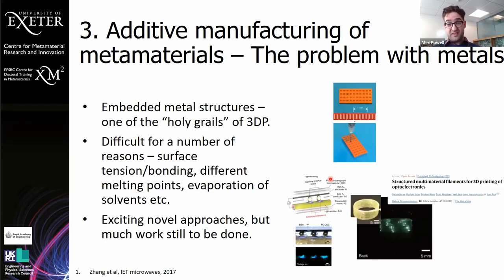In terms of embedding structures, this is still something that's really, really difficult. And I would say that there's a lot of people working on different methods for this, but as far as I'm aware, a satisfactory way to make metal inclusions still remains to be achieved. And it's really difficult for a number of reasons. Like, you have to have surface bonding between your different layers. So this is actually quite hard to achieve between a lot of different metals and different materials. They also have radically different melting points. So you can't have a structure where you have a metal and a polymer powder being sintered with a laser at the same time, because there's about a factor of five difference in their melting temperatures.